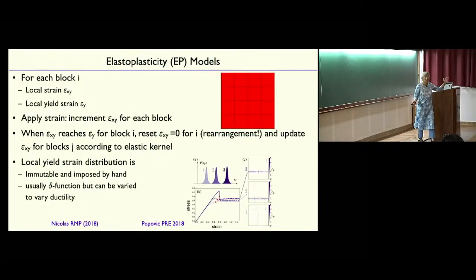Now, people have developed elastoplasticity models where on each block I, each lattice site, you have a local strain, okay, you have a local yield strain, and now you just increment the strain, and as you increment the strain, once the strain exceeds the yield strain, you say, I rearrange, you set the strain equal to 0 on that lattice site, and then you have an elastic kernel, this quadrupolar thing, right, that distributes strain everywhere else. The strain that was released here gets distributed elsewhere. So you have an elastic kernel.